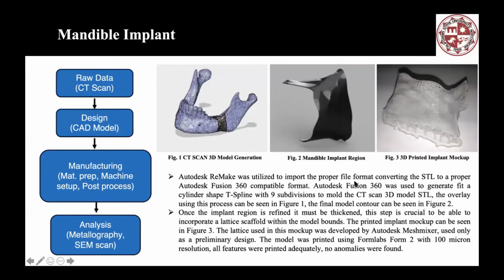We converted this CT scanning file to STL, and then converted this STL file to the proper format in Fusion 360. We use Autodesk 360 to generate a cylinder-shaped T-spline with 9 subdivisions to mold the CT scan. Figure 2 shows the mandible implant region. Later on, we used the Formlabs Form 2, the resin SLA 3D printing, to print out these samples. This is the implant mockup.